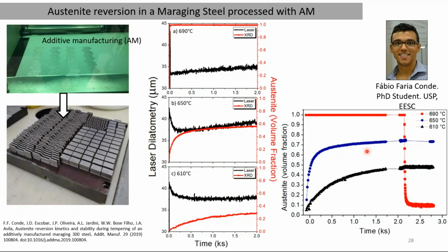With this graph, we can better design, for example, this reversion of austenite. I can choose a lower temperature in order to affect my material less, and I can choose a shorter time to produce, I don't know, 20% of austenite, let's say, a stable 20% of austenite. So I can produce some amount of austenite in a specific time. Doing these tests, I'm able to say that, for example.